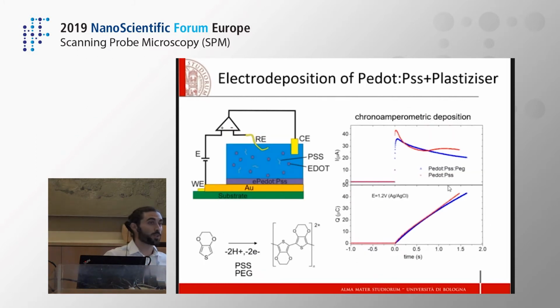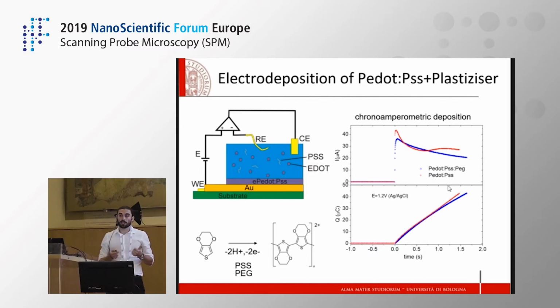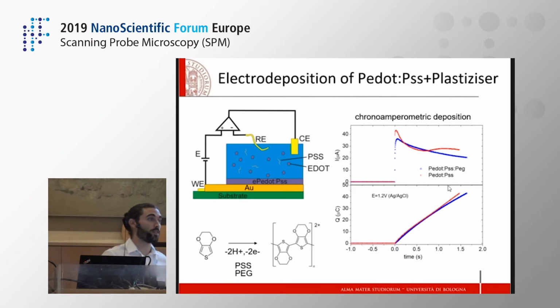In particular, an important step of the fabrication is the electrodeposition of PEDOT:PSS PEG. We use an electrochemical deposition starting from PSS, EDOT, and PEG molecules in a water solvent, and we introduced two improvements. We did a thickness-controlled deposition in an inert atmosphere. In this case, we flux nitrogen in order to avoid the oxygen-related termination of the PEDOT chain that could lead to shorter chains and thus to an easier delamination of the polymer. We fix the thickness of our polymer with a chronoamperometric deposition, fixing the voltage at 1.2 volts and then integrating the current, thus calculating the charge that we are depositing and fixing the charge amount that we want to deposit, thus the thickness of the electrode once we know the area we are depositing on.